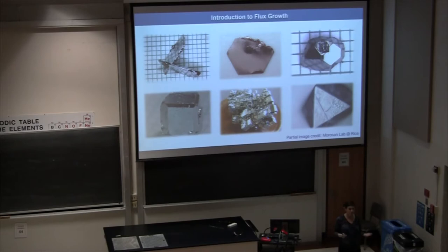So what's great about this is that if I want to throw this sample into the PPMS or the SQUID, I don't need to do a Laue measurement to align it. I can do it by eye. I can look at this crystal and know its orientation, and that can save a lot of time. So other crystal growth techniques don't necessarily give you this nice access to the habit of the crystal.